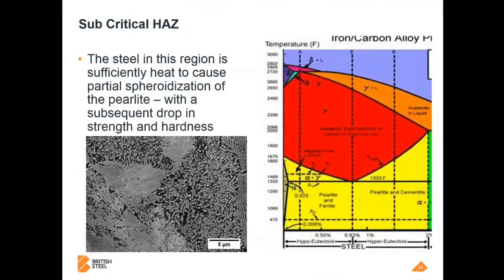You do have some slight decomposition of the pearlite. The lamellae start to break up and shorten. You get some spheroidization, but the further away from the weld you get, the lower the temperature and the more and more like the bulk microstructure.